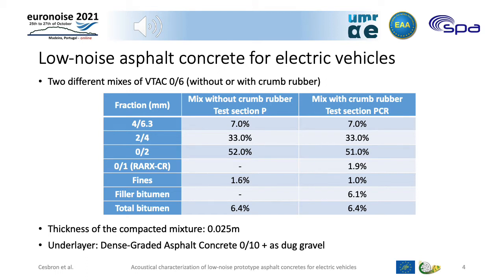As you can see in the table, both mixes are based on the same formulation, but one contained 1.9% by weight of crumb rubber. The test section without crumb rubber is named P, while the test section with crumb rubber is named PCR. The thickness of the compacted mixture is 2.5 cm, while the underlayer on the test track is a dense graded asphalt concrete 0/10 plus as dug gravel.